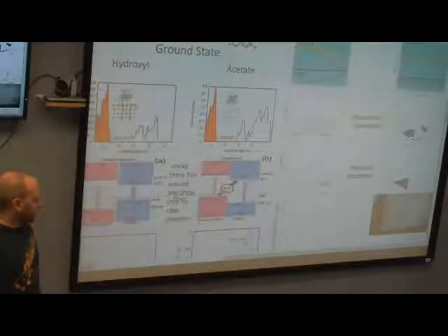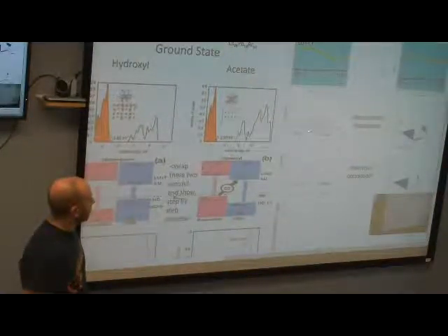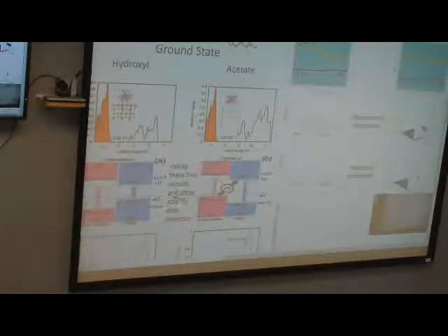So I basically cut out all of this stuff in the hydroxyl one, so I've got figures now that look more like this. Do these labels for my indices make sense, I guess? Is it kind of like clear what it is that I'm representing with those? Yeah. Okay. So this is showing the electron dynamics as it relaxes. It's just showing you which orbital, or the occupations of each orbital at some particular time. So as time goes on, you can see that it kind of transfers down into lower energy orbitals and ends up in the LUMO eventually. And I'm gonna change these to be more like LUMO plus whatever.